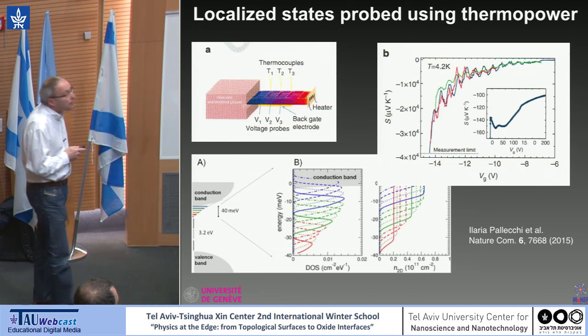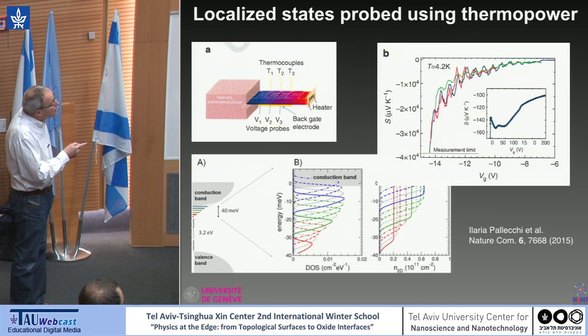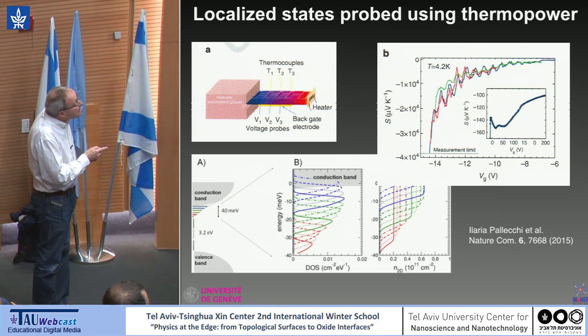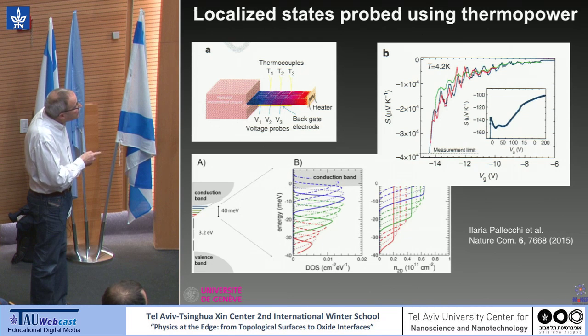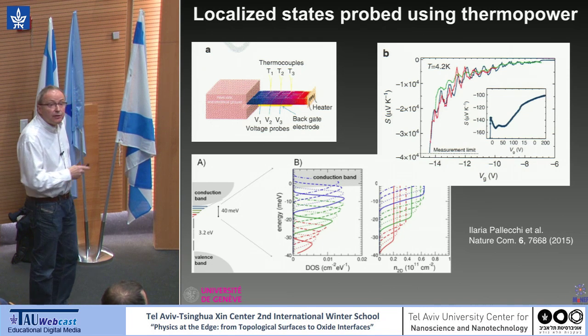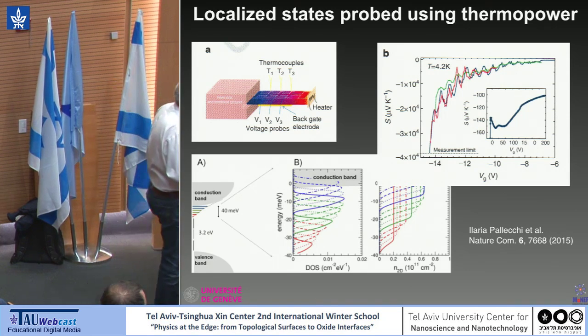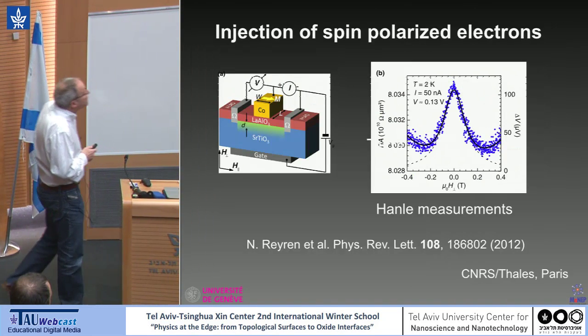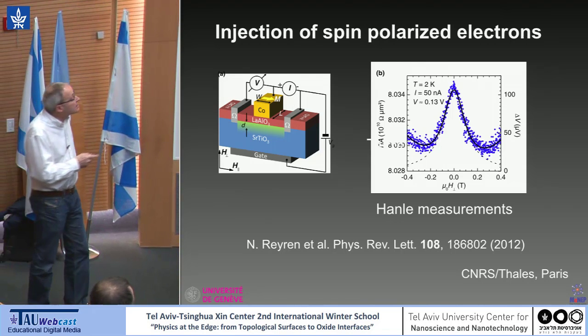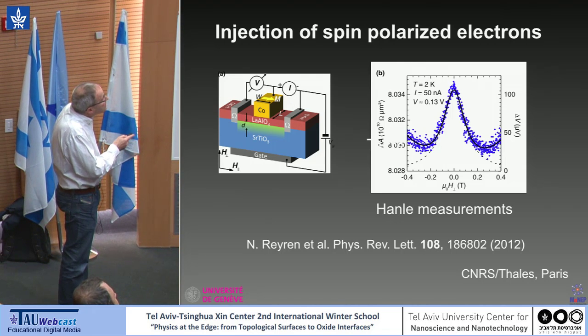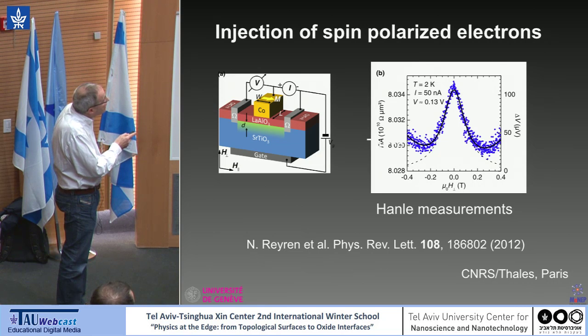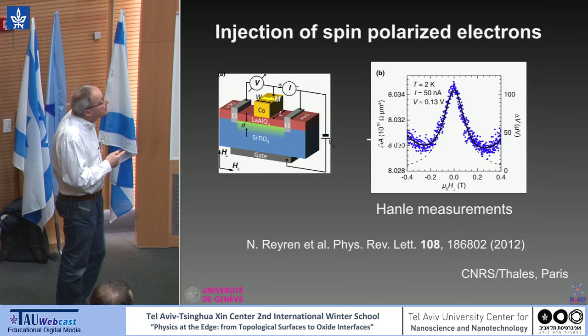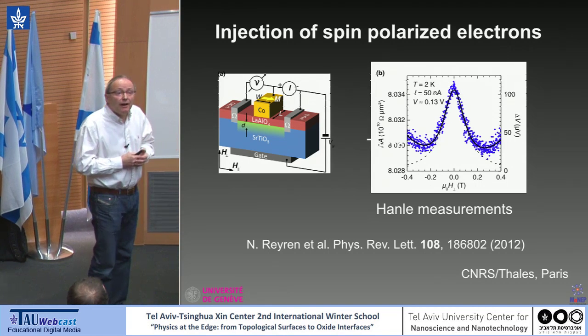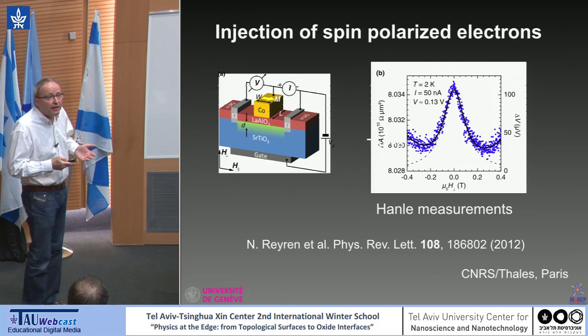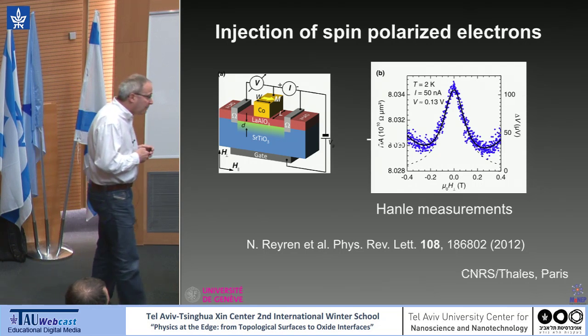Seebeck coefficient, thermopower, has been measured in the system with giant values and giant oscillations, which could reflect localized states that you have at the bottom of the band, maybe some of the missing electrons. And let me also mention that spin injection has been tried in the system. You see here results from Paris, where you use a cobalt electrode, you inject spins, and you measure the spin imbalance using the Hanle effect. The dream would be to control the spin polarization using the Rashba effect. But unfortunately, the lifetimes are very short.